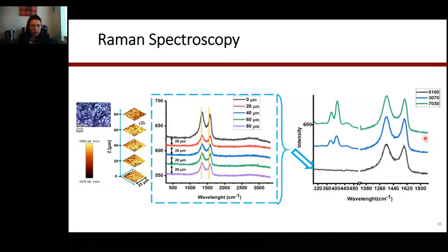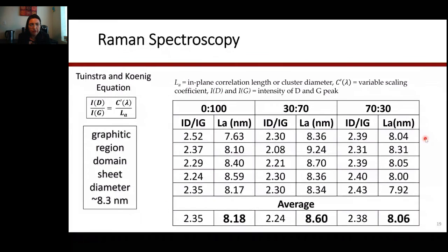So why was this study important? Why am I talking about this vibration? Once we want to learn about the electrical characteristics of it, we need to understand how big those graphene sheets are. And using that data, we can obtain the average size of the graphitic region. That is about 8.3 on average that we got from our samples.